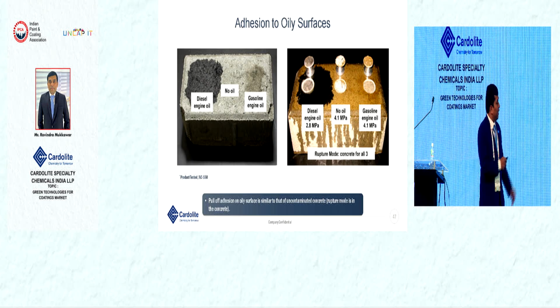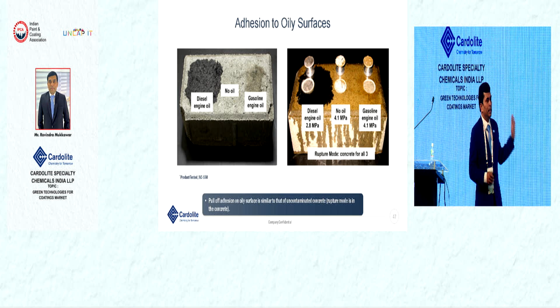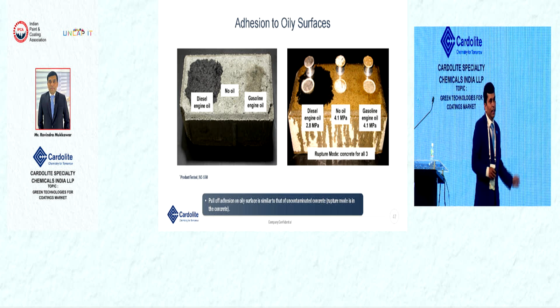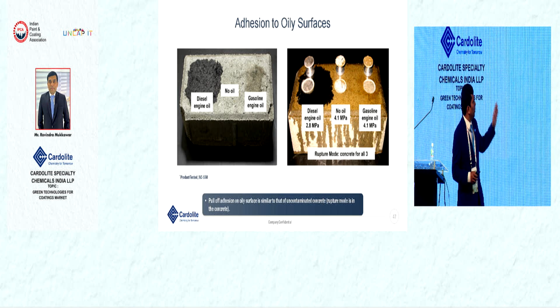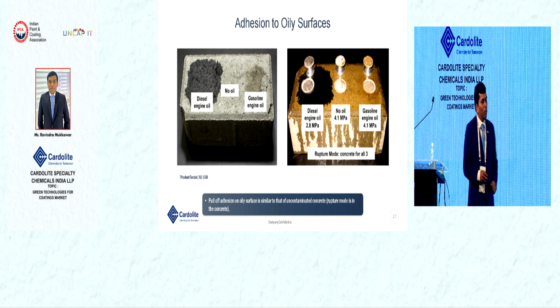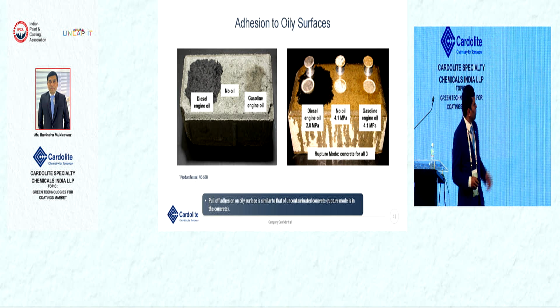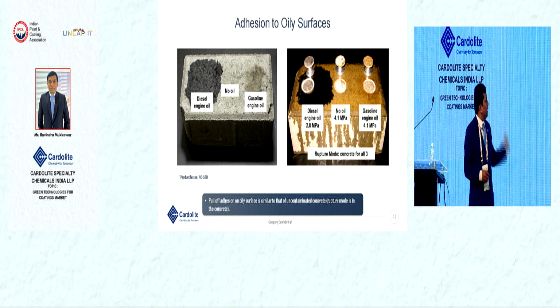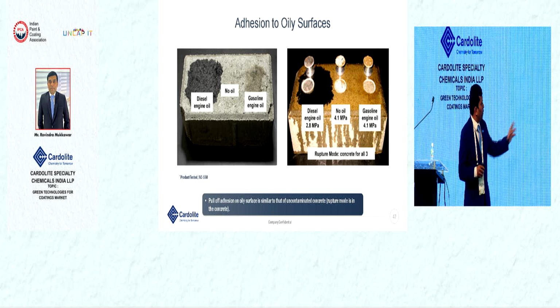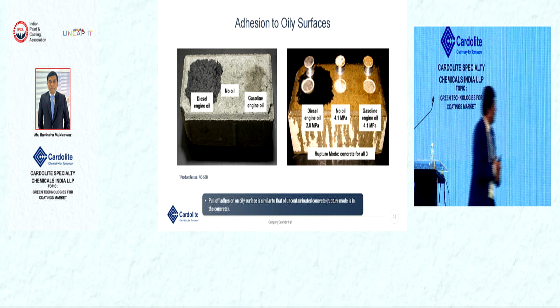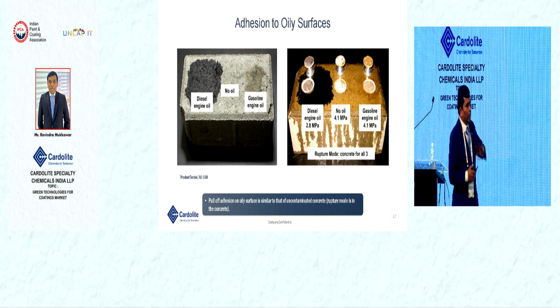So look at this adhesion performance. We checked the NC558. We checked diesel engine oil, gasoline, and then we applied our clear primer and we checked the dolly test. So it passes 2.8 MPa in the diesel, 4.1 MPa in engine oil, and gasoline was 4.1. So there is good adhesion on the oily concrete surface.